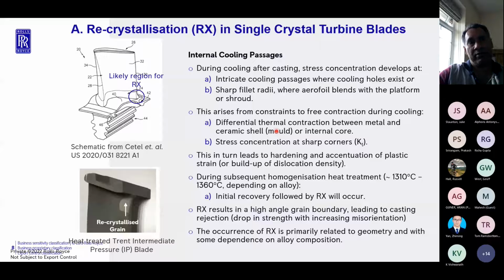So you've got a thermal misfit that exists between the metal and the ceramic in these internal cooling passages. At the same time, you've got very sharp fillet radii where the turbine aerofoil blends with the platform. So potentially you've got regions in the casting where stress or plastic strain can develop during casting. Now, all that is fine in the casting. You've got plastic strain. So what? As far as the casting is concerned, that doesn't cause any harm or any detriment.